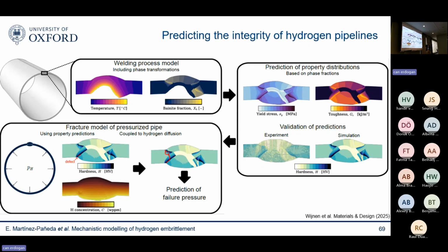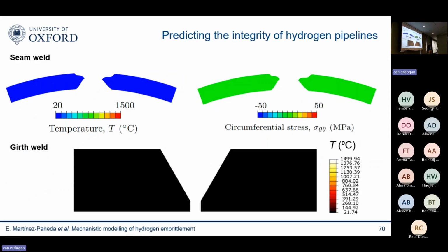So models seem to be useful here, and in order to answer that question, basically we created a framework where we combine those phase field models for hydrogen embrittlement that I've shown before with welding process models. So you simulate the welding process, then it gives you a property distribution within your weld, the different phases, the different heterogeneities that you have in there. It gives you residual stresses, and then you run the simulations with increasing pressure and predict when the pipelines will fail.